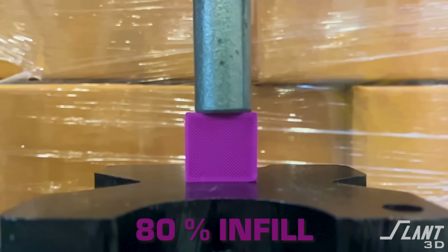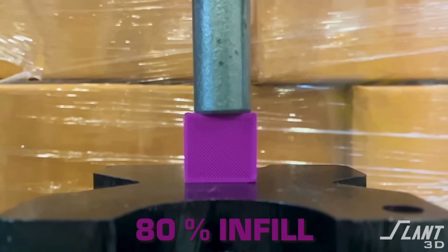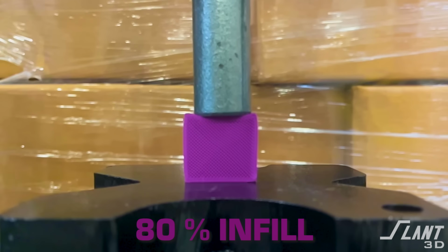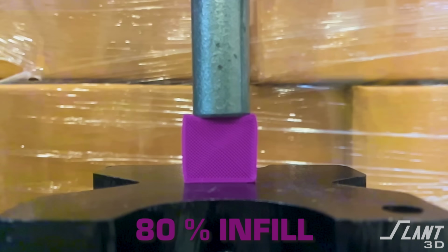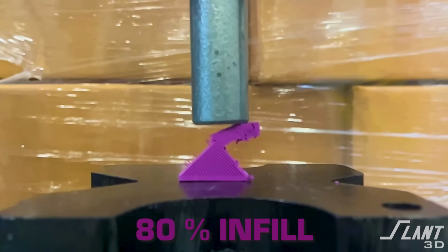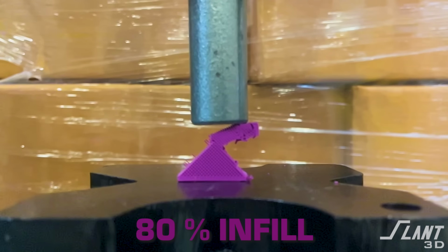Now we'll just go up to 80% infill. Our sensor was no longer able to measure at this level because it wasn't able to support more than about 500 to 600 pounds of force. 80% here on a steel bed with full compression, you have a failure and then catastrophic failure, shearing along the diagonals immediately, leaving a perfect triangle behind.